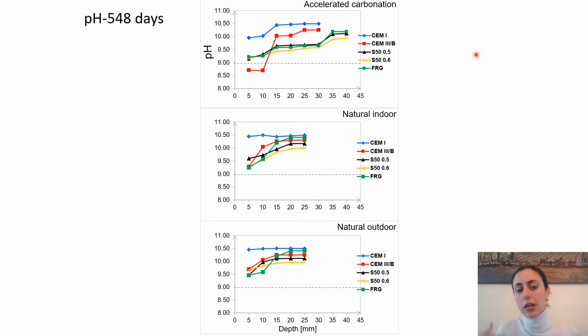So we know that the carbonation mainly induces drop of the alkalinity in the pore water of the concrete. And here you can see for the accelerated carbonation. So once we had the carbonated layer of 35 millimeter, the pH was evaluated basically on every 5 millimeter from the top surface by grinding and dissolving it and then testing the alkalinity.